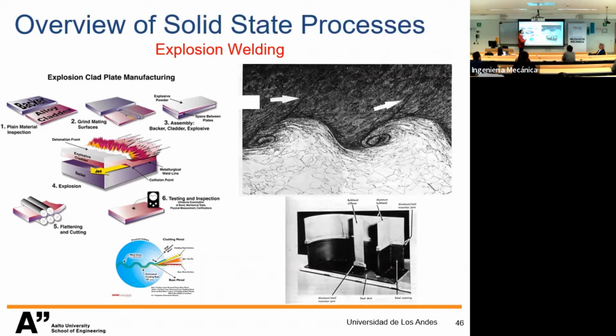That plastic deformation generates a chemically active surface, and the heat is such that you can see this wave shape, almost the behavior of a liquid interface, because it's this third body domain that behaves as a liquid, but is solid in temperature. And there is a significant amount of diffusion between the layers and high power. The joints produced by these solid state solutions are typically of the same level or even better than the base material.